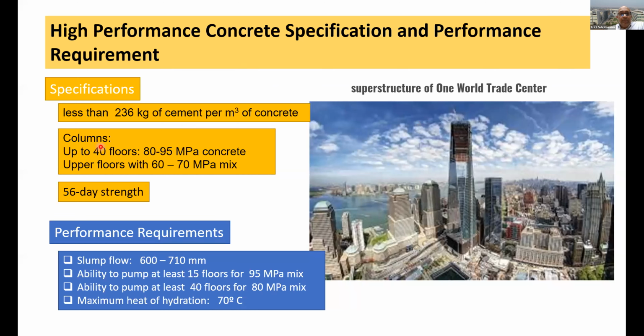In addition, the requirement was that columns up to 40 floors had to be of a concrete of 80 to 95 megapascal strength. The upper floors were 60 to 70 megapascal mix. Of course, these are 56-day strength. And in a later part of my presentation, we'll see why 56-day is important. And of course, the performance requirements are here.